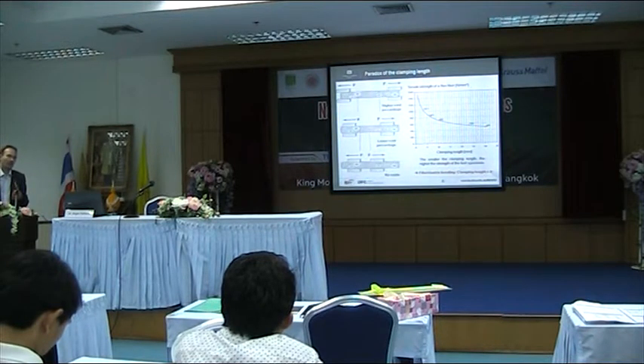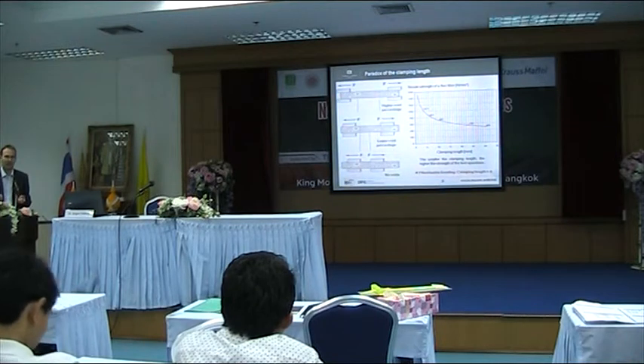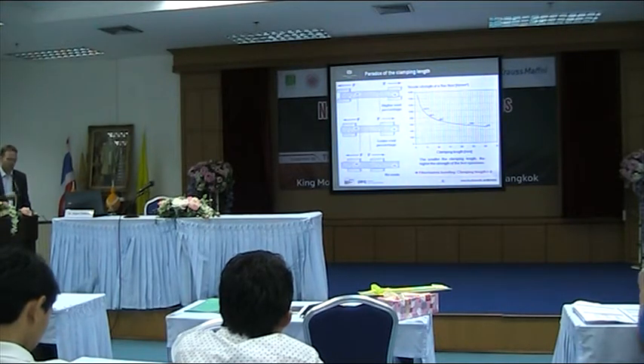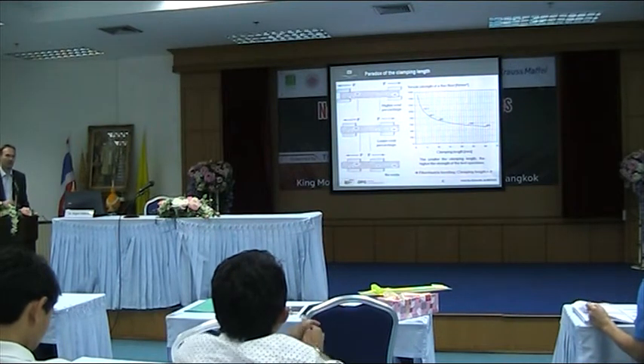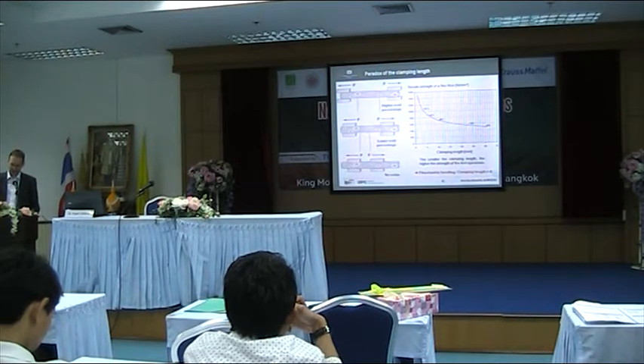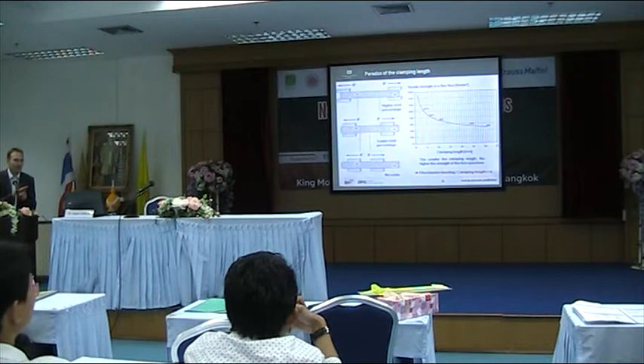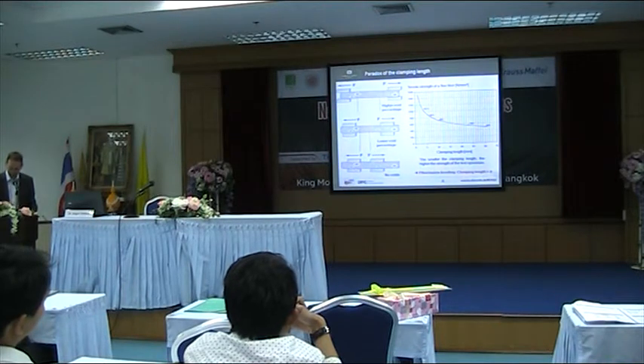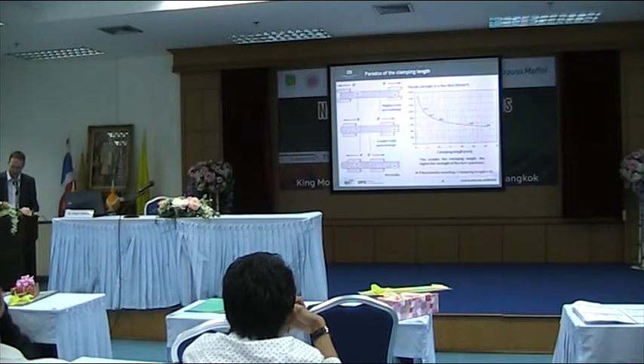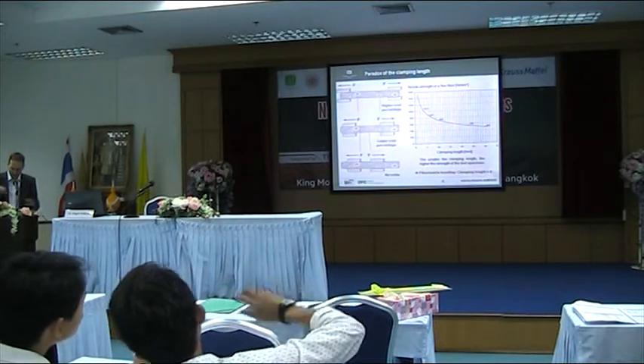But when we think of going to composites with longer fibers, we have to take a textile prepreg, textile material with longer fibers, and then the impregnation, especially with the thermoplastic melt, is a big issue to reach high specific properties. And this is something I will speak about later. So first is to get good fibers with as low as possible a diameter, and as low as possible a free clamping length, meaning as good an impregnation as possible for the reinforcement effect, especially to get good tensile modulus and tensile strength. Okay, so this is something theoretical, but with these paradoxes you have a basis to get good composites.